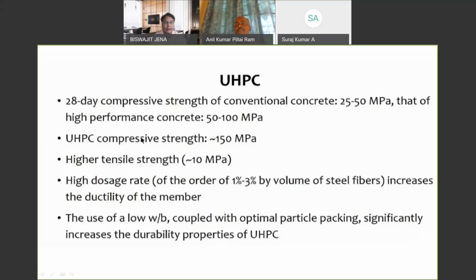And also you can add quite a bit of steel fibers to these materials so that you can increase the ductility of these members. Also, the water binder ratio is extremely low, which will help to get a very high packing and very low porosity. So it is a combined effort of reducing the water cement ratio, improving the particle packing, and using steel fibers to improve the ductility.